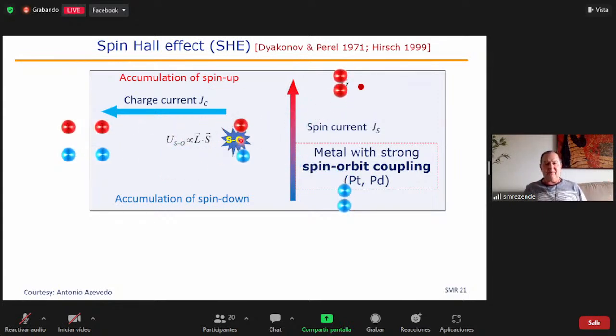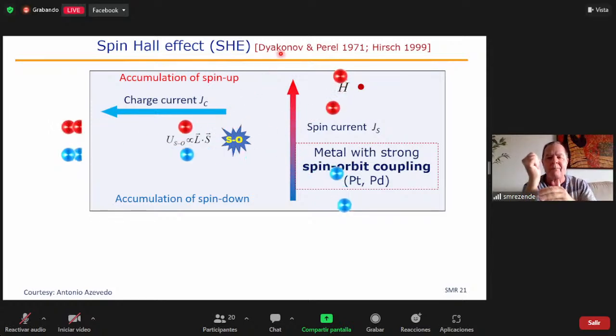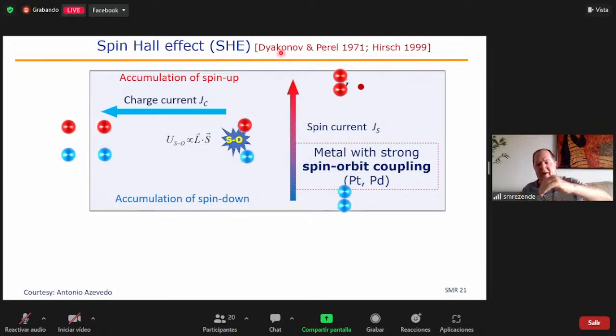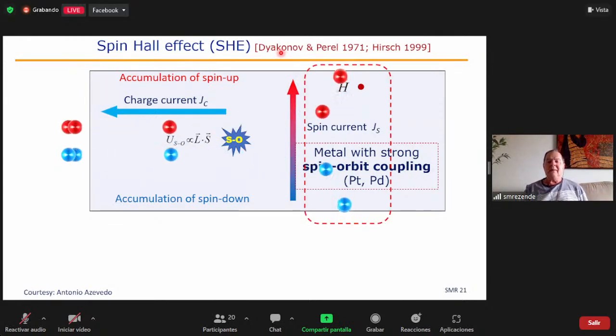If we have a heavy metal like platinum or palladium, they have a strong spin-orbit property. So the collision of electrons in the material will be sensitive to the spin-orbit. This means that an electron with spin up will be deflected upwards because this produces angular momentum up, and the electron with spin down will be deflected downwards because the angular momentum is in the opposite direction. And notice that here we have a spin current. So the charge current has been converted into a spin current.